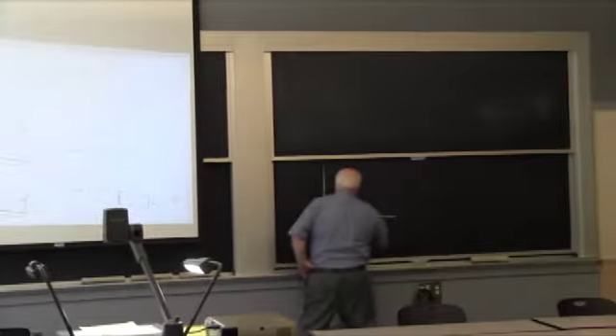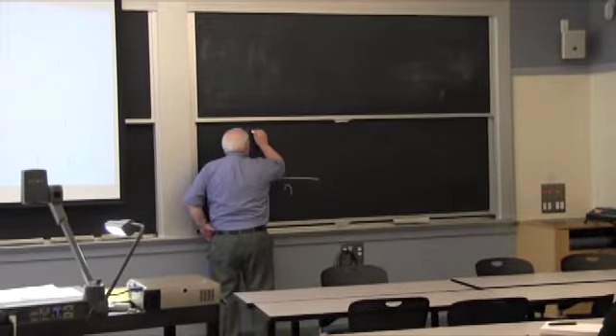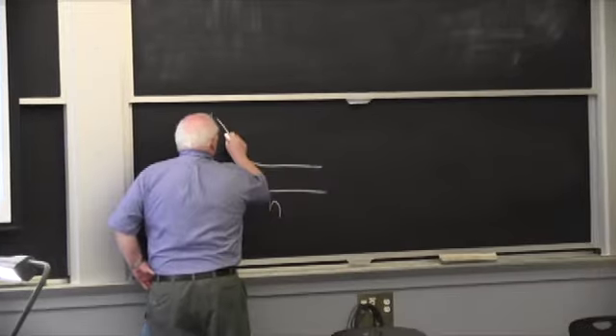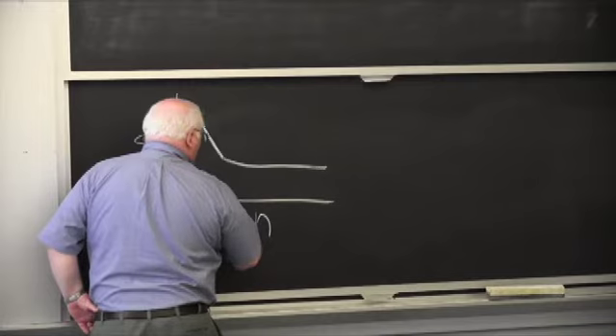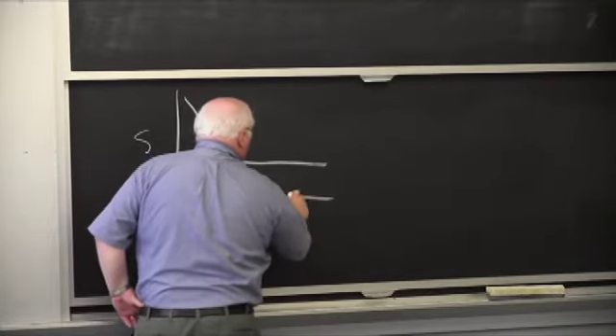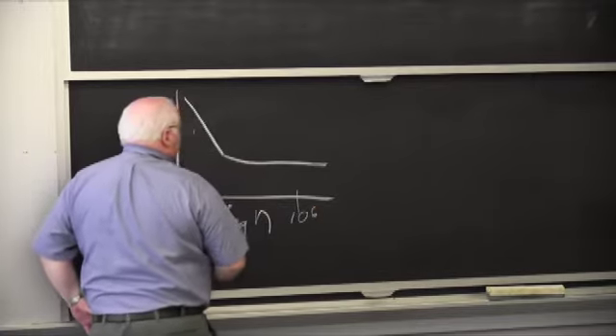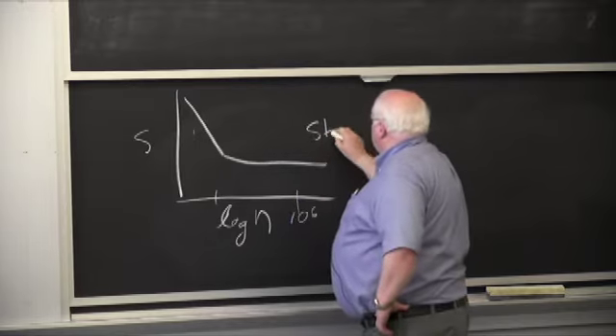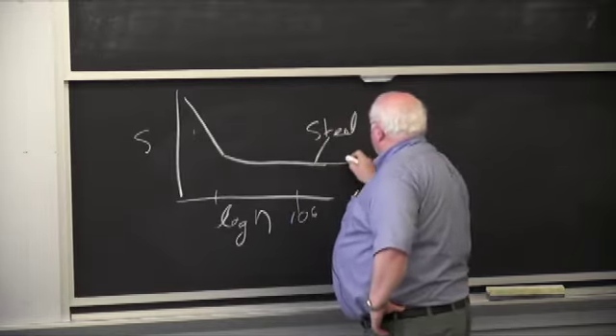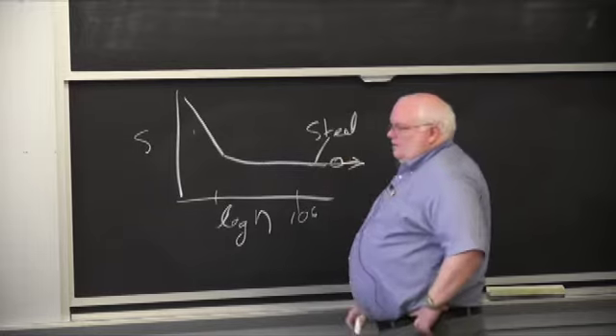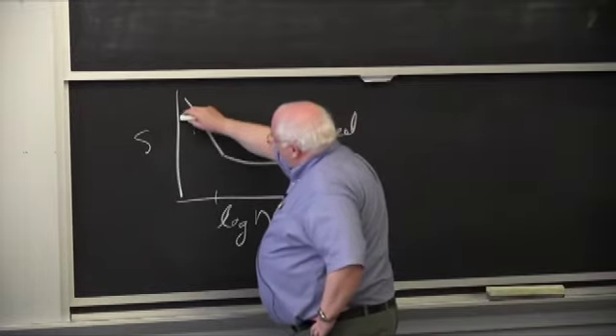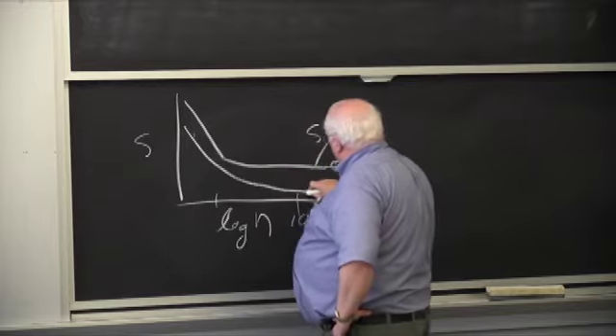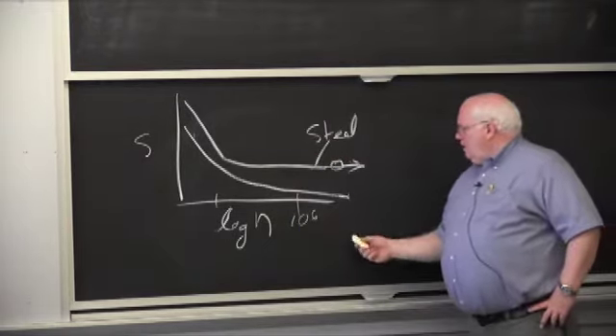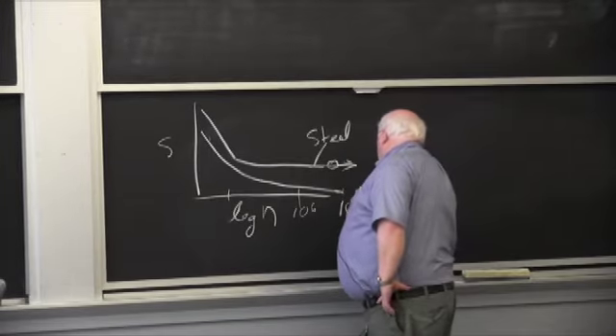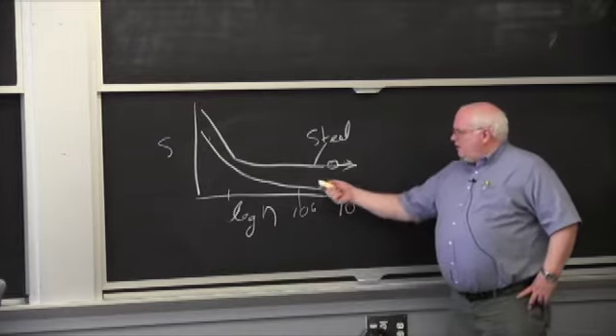No one? Okay, well, you will learn at some point that if you look at the stress versus number of cycles, for steel you get a fatigue curve that comes down and looks like this. And so this is high stress and low numbers of cycles. This is log cycles. So somewhere around 1 million cycles or 10 million cycles, the thing levels off for steel and has essentially infinite life, which they usually draw as an arrow going out. For aluminum, you'll be considerably weaker, but the curve just keeps going down. And people have gone out to 10 to the 8th or 10 to the 9th cycles. Takes a long time to get 10 to the 9th cycles. But in any case, it just keeps on decreasing.